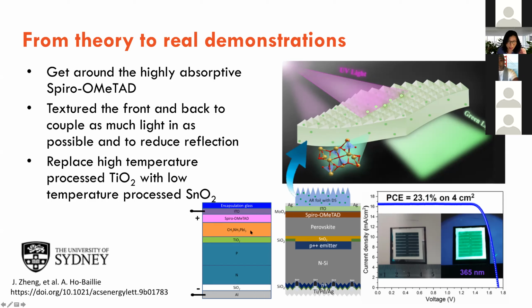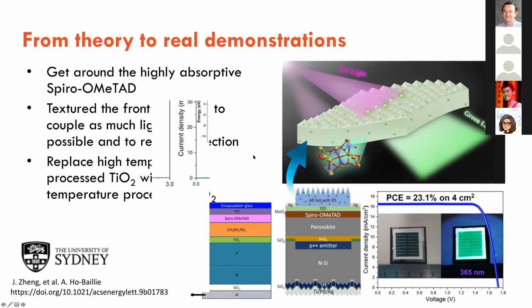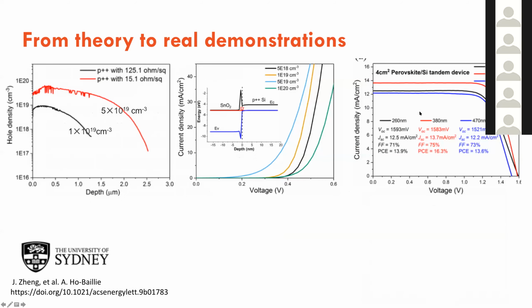Also, you can see, you know, in theory, we look at titanium dioxide, but in practice, we have got to use tin oxide. And the reason is titanium dioxide, you know, it requires 500 degrees for processing. So it's not very good. It's expensive and it's bad for the silicon cell on the bottom. So we replace it with the tin oxide as well. And yeah, looks easy. We get 23%. But of course, in reality, there's a lot of research being put in.